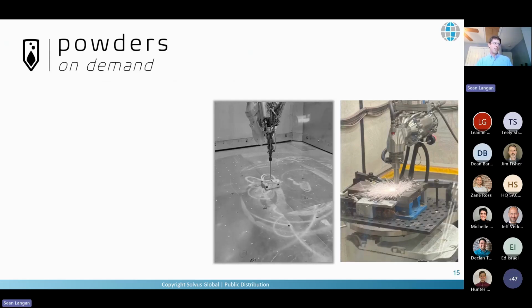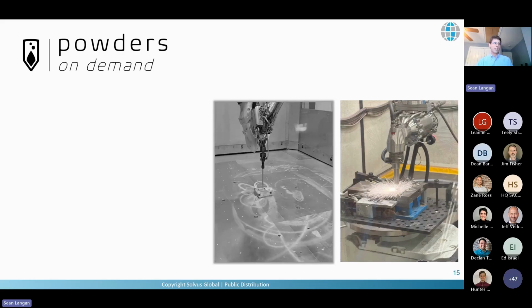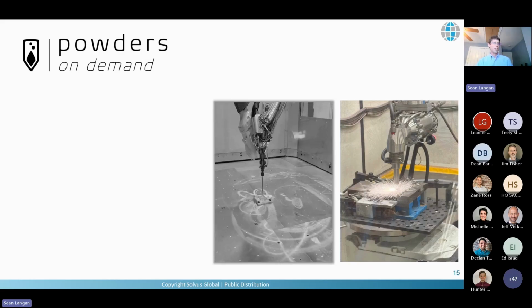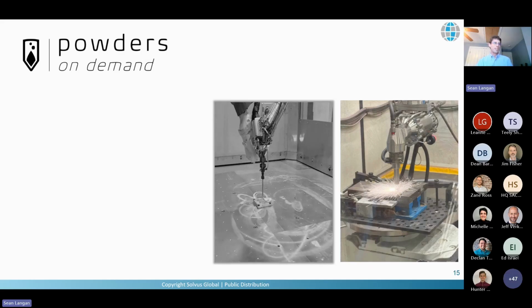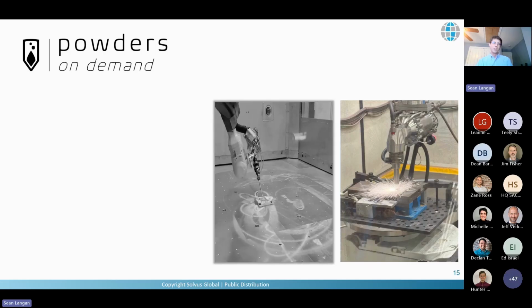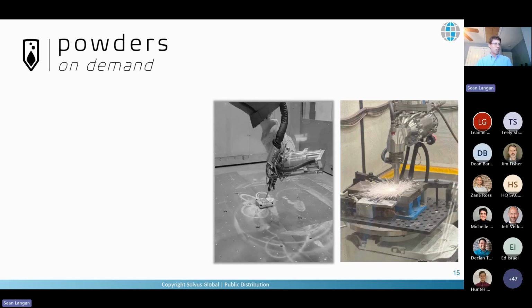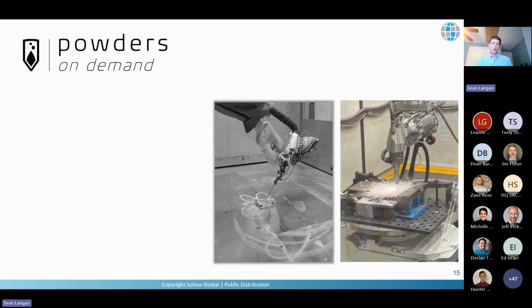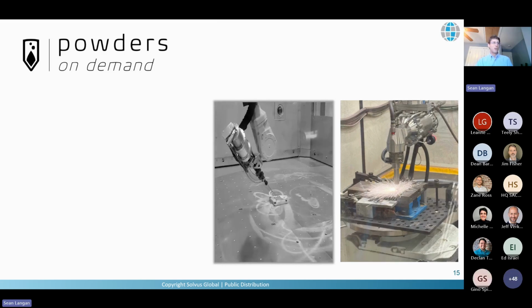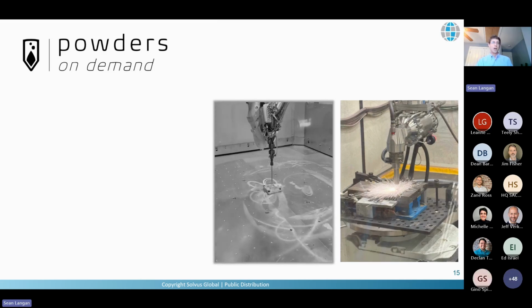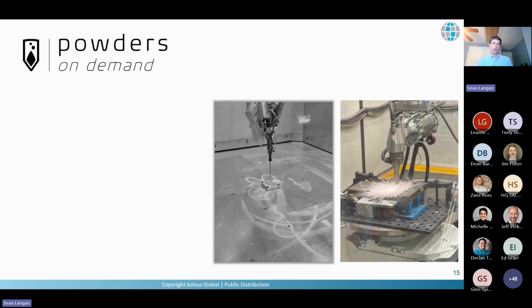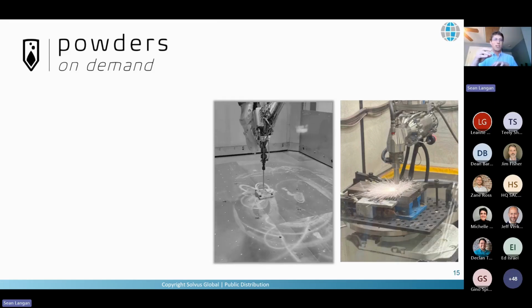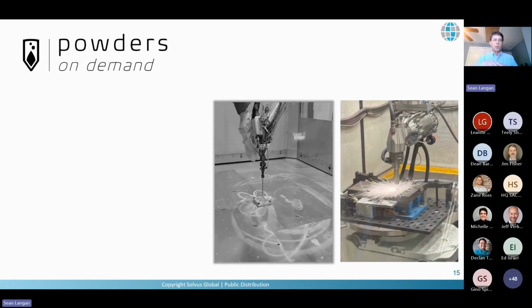Cold spray is another additive manufacturing and coating process that, if you're not familiar with it, takes metal powders and accelerates them at supersonic velocities. And then when they hit the substrate, they bond to it. They form a metallurgical bond with it. It's a solid state process, so there's no melting. You maintain your microstructure from beforehand. There's very low heat affected zone. So there's a lot of real benefits to it.